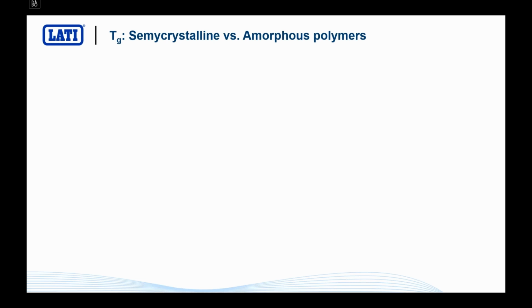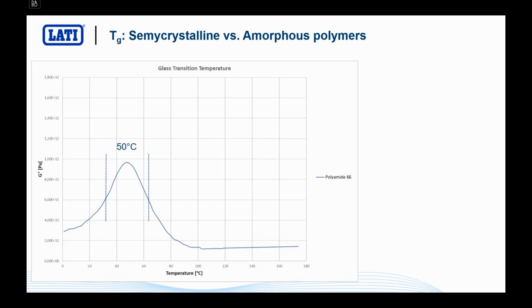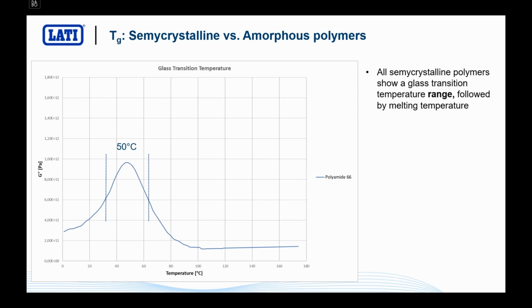Now, we are at the end of our webinar. We are going to talk about what happens with the amorphous plastics. First of all, we have to focus our attention on the main difference between amorphous and semi-crystalline, not only from the morphological, but also from the thermal point of view. The semi-crystalline plastics have a glass transition temperature range, which is set by the formula of the polymer itself. And we must keep an eye on this glass transition temperature because we want to set the mold temperature of our tool 10, 20, 30 degrees above this temperature, if we want to have a very good looking part.